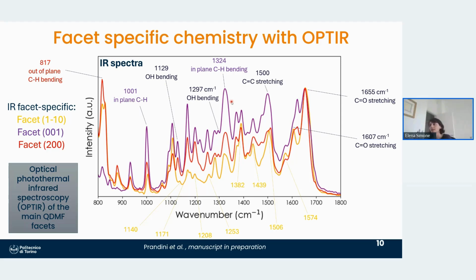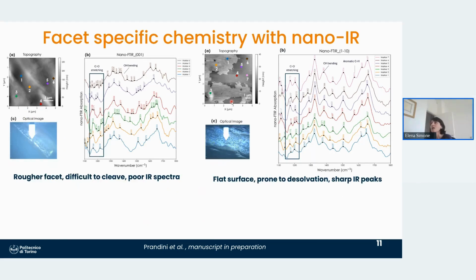Then, linking these directly with the modeling is something that we are working on, because it's not that easy. We also tried nano IR. On the same facets, we did AFM combined with IR, so we get an IR spectrum of a point on the surface of the crystal with the same resolution of AFM. This one, to be honest, didn't work so well. You can see that this is our 001 facet, the capping facet, the one with the OH groups, and this is the 1-1 0, the large one with the DMF molecules.